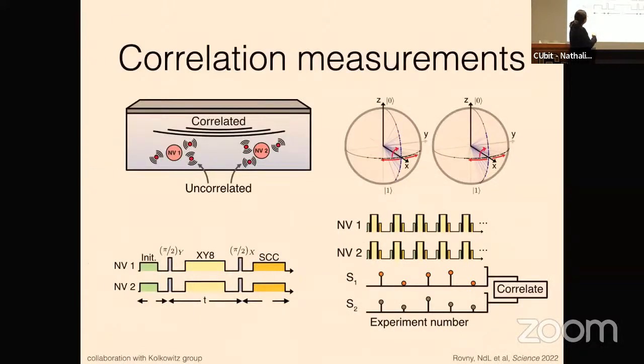Okay, so the setup is I have 2 NV centers, and each of them is staring at some kind of correlated noise bath of interest. And then they each have some uncorrelated noise that we don't have control over, usually things like nuclear spins or electron spins that are in the vicinity of the NV centers. Now, what we can do is basically just a Ramsey experiment. So we take both of the NV centers and put them on the equator of the Bloch sphere, let them accumulate phase, and then now, in order to look at correlations, what we want to do is instead of just